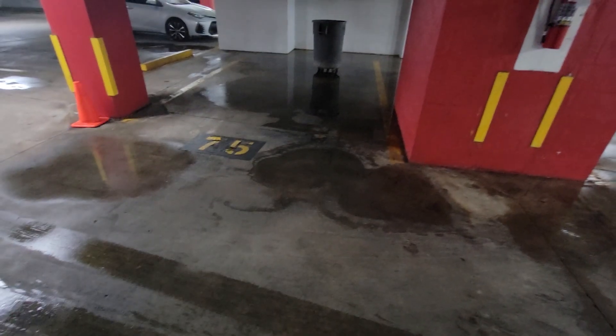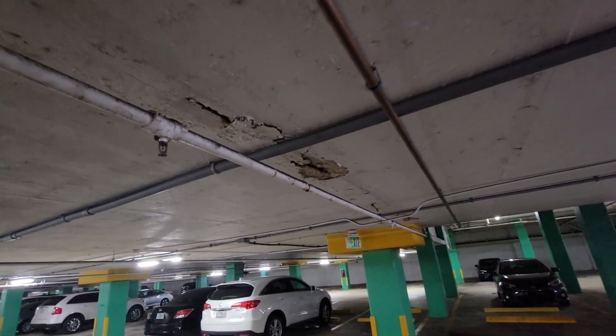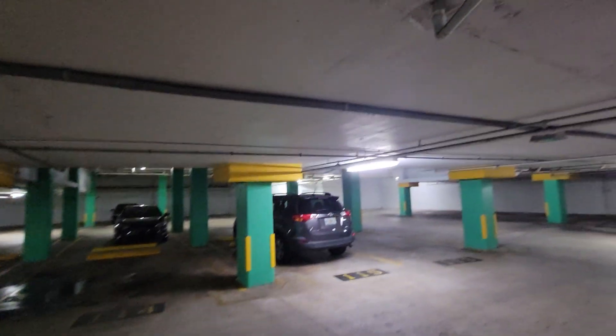At some point, when you see chunks coming down that means they end up on the floor — somebody should have said 'we've got stuff falling off the ceiling, we better look at getting this patched.' I don't know why they haven't. I'm starting to see cracking right here — this concrete is just hanging and resting on top of the conduit, otherwise it would have fallen off. The spalling continues over about 10 feet total, some visible and some not. This is what we see a lot of in garages down here in South Florida.